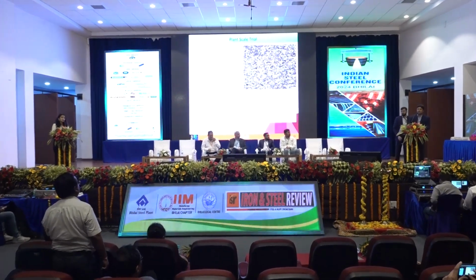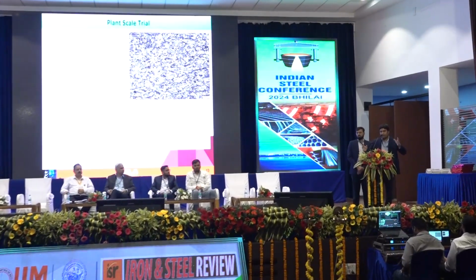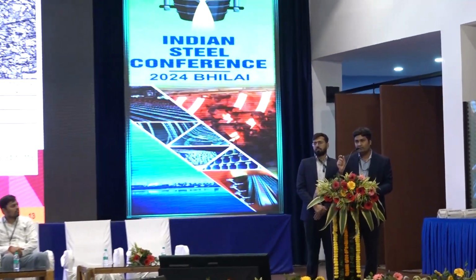So we do this process in the batch annealing process, which is an enclosed surface, and we inject nitrogen or hydrogen gas as a heat carrier source. So that homogenizes the whole container in which we place the multiple stacks of coils. Even though, because we are in the same field, in my opinion, there should be one more step in between. That can be, but in our case, we can achieve it, and also our batch process is stacking multiple charges. By doing that, you can reduce the soaking time also, from 12 hours, 14 hours, 16 hours, by having a homogeneous temperature at the intermediate temperature, so we can do homogenization, that fine carbide structure. Okay, sure. Thank you.